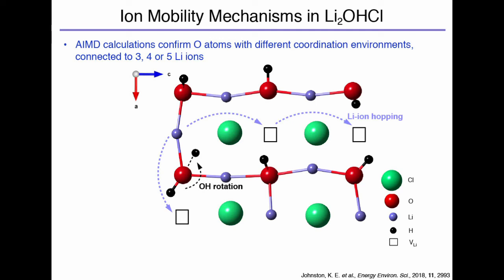Okay, so putting all this together, what does this actually mean? So we think that we have a mechanism for what happens in Li2OHCl and why it could be a potential ion conductor. You start at lower temperatures in the lower symmetry structure, orthorhombic or tetragonal, who knows, that's up for debate still. But as you increase the temperature, you undergo that phase transition to cubic structure. That alone is not enough to get this enhanced ionic conductivity. You still need more temperature to get those lithium ions to move.